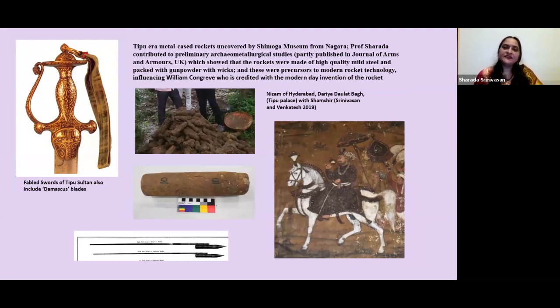And I should add, as an archaeometallurgist, it's also a matter of satisfaction that I could play a bit of a role in the study on the Tipu era rockets, the metal cased rockets, which were uncovered by the Shimoga Museum from Nagara. And then this was a paper that was published by Shejeshwar Nayak and Olikara, to which we contributed. And what we were able to show is that the rockets were made of high quality mild steel, and they were packed with gunpowder, you know, a mixture of charcoal and sulfur and saltpeter along with the wicks. And of course, these were unfired rockets. So this was also quite an exciting study.